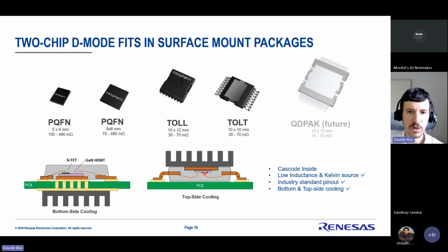So now the silicon FET, the HEMT, the lead frame is facing up, and now we can put the heatsink on top of the package and leave the PCB free to be used for electrical routing. So this is decoupling the electrical from the thermal management, and it's a very elegant solution, and we see a lot of interest from this technology.